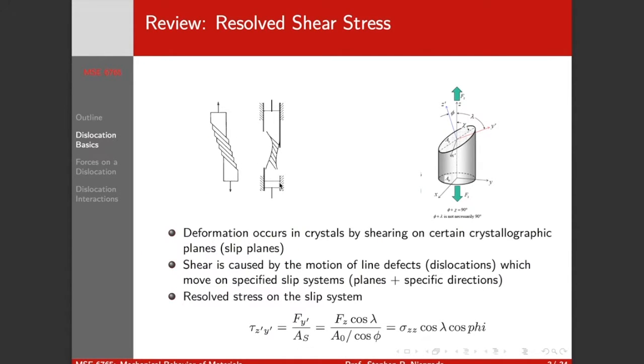So just a definitional thing, the resolved shear stress, we probably all remember this. But it was observed that deformation in single crystals occurs by shearing on certain crystallographic planes or slip planes. If we pull on a single crystal in tension, we get these stepped interfaces, parallel lines that appear along a certain direction.